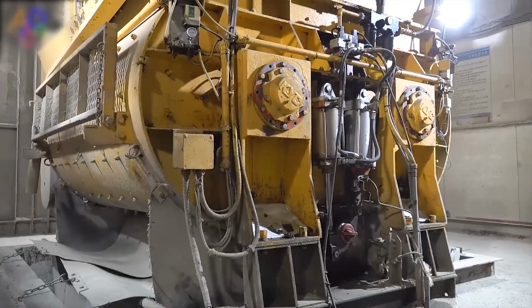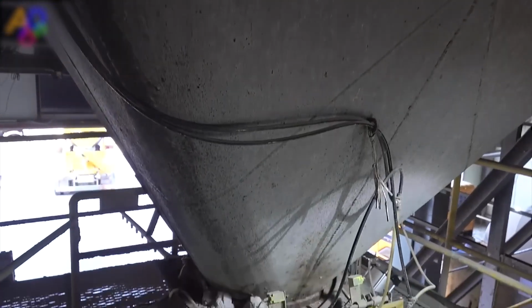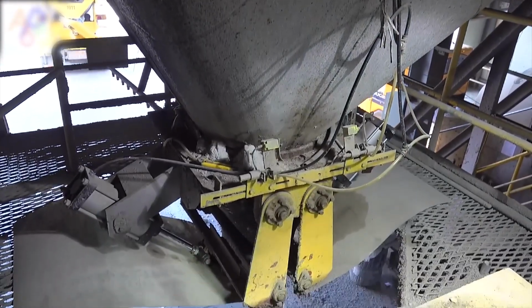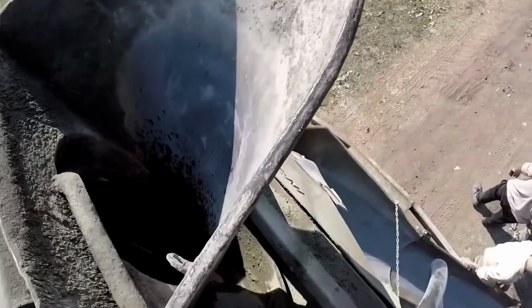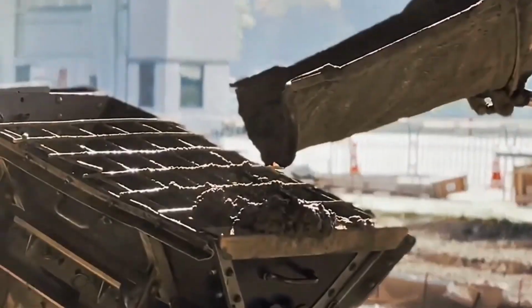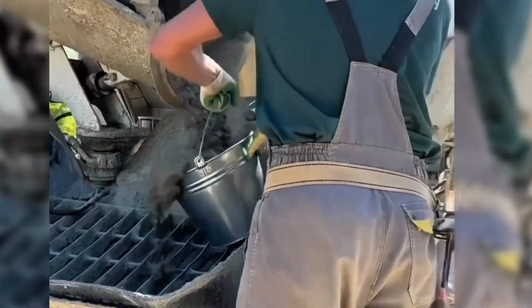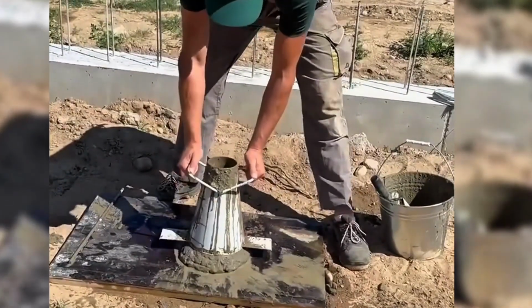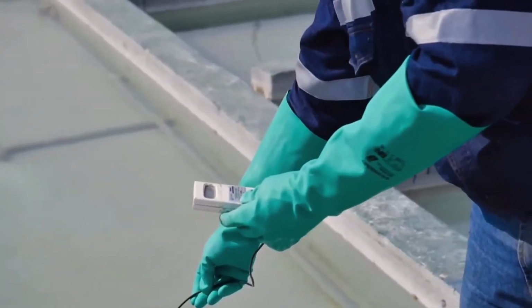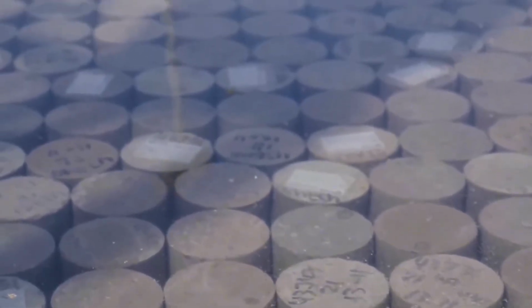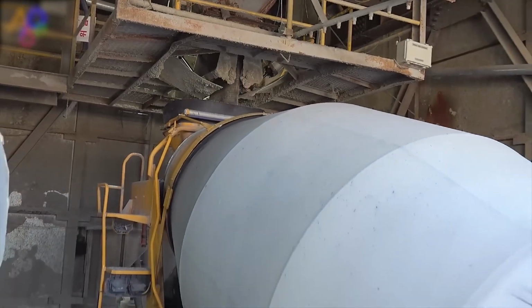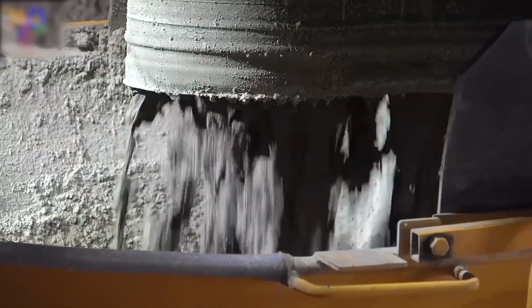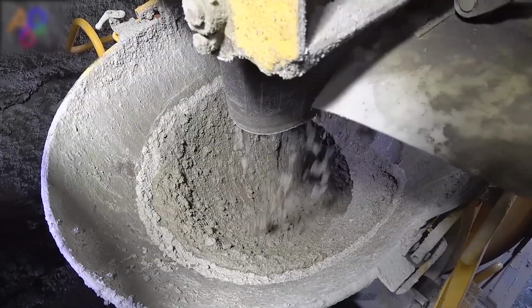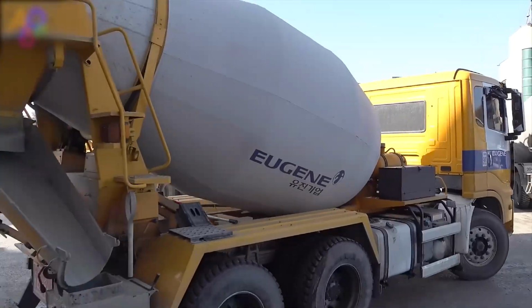Every concrete mixer carries its own water supply, typically 400 to 600 liters in a pressurized tank. This water has two uses. First, minor slump adjustment. If the concrete arrives slightly too stiff for the pour conditions, a precisely measured amount of water can be added. ASTM C94 allows this but strictly controls it. The water must be added before the 300 revolution limit, and the drum must turn at high speed afterward to fully distribute it. Adding too much water destroys the water to cement ratio, which directly determines the final strength of the cured concrete. Second, drum cleaning.